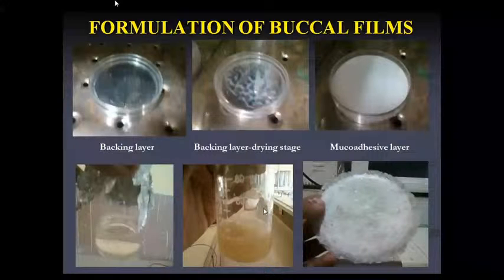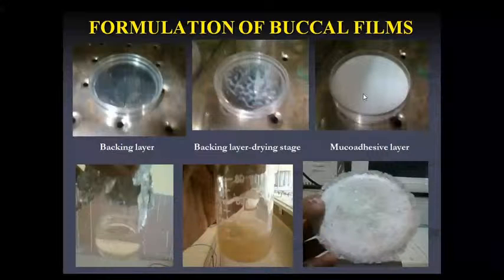So what happens once we transfer over this backing layer? It takes a long time, maybe around 12 to 18 hours. Once it gets evaporated, then it can have this. This is the bilayer. Why bilayer? Because we already made the backing layer. Again, above that, we transfer this one on top of the backing layer. Again the mucoadhesive layer is formulated, so that it is known as the bilayer buccal film.